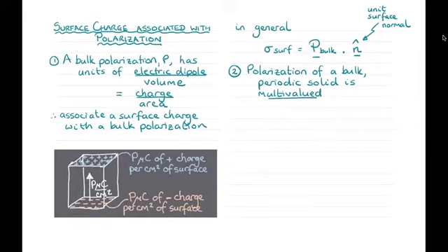So we can write it as some P0, say, plus N times PQ, where PQ is the electronic charge times any lattice vector divided by the unit cell volume, and we call PQ the polarization quantum.